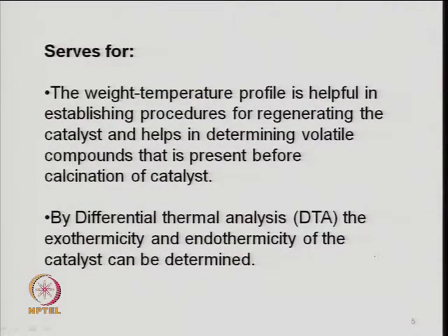In general when we look at a catalytic activity, we are interested in determining the weight loss as a function of temperature or time on stream, right. Then you can have the idea about the calcination temperature. If you have a hydrogen stream, you can get the idea about the reduction, and that will be similar to your TPR study, right. If the coke is deposited on the catalyst and you want to study the kinetics of the coke removal by gasification, you can do the kinetics in the TGA apparatus, right. So, the weight temperature profile is helpful in establishing the procedure for regenerating the catalyst and helps in determining the volatile components that are present before calcination of the catalyst.